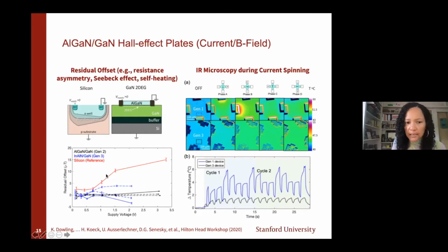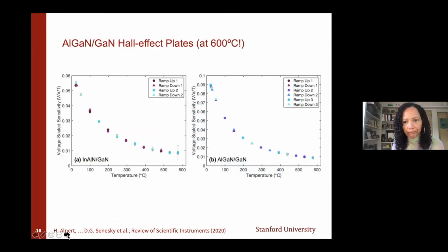But nonetheless, in comparison to silicon devices that, again, suffer from Seebeck effect, we are dramatically reducing this residual offset. And again, we attribute that to reduced thermal gradients and also reduced impact of the Seebeck effect in our Hall effect devices. So we've also operated these Hall plates at elevated temperature.